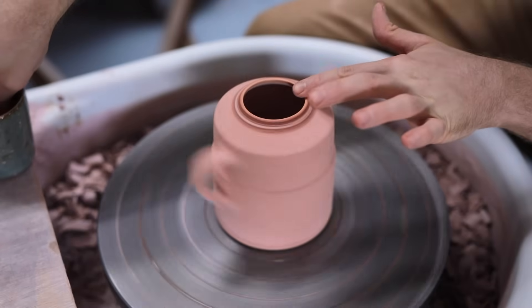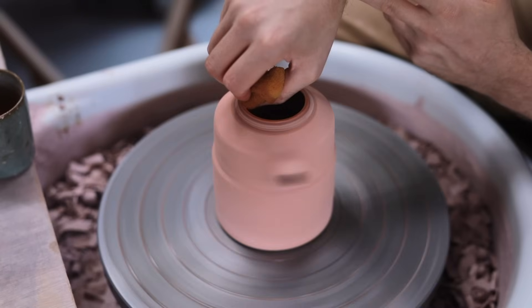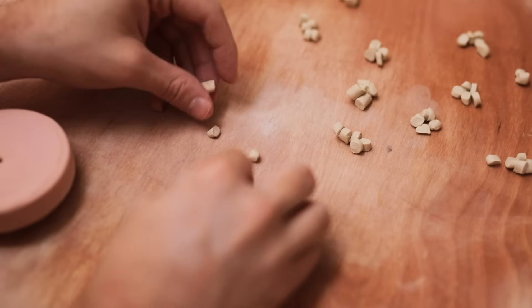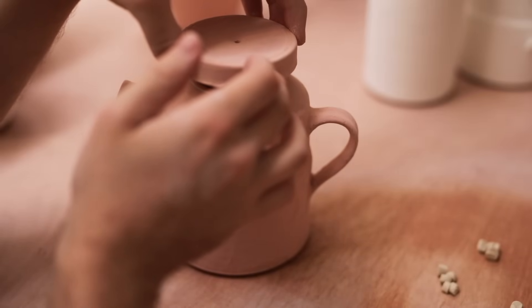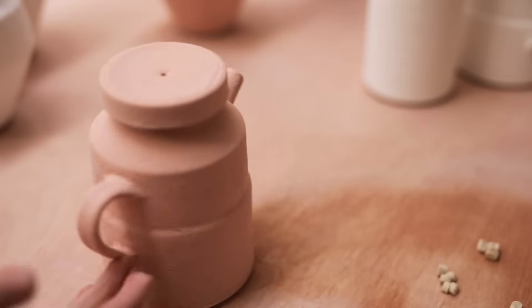I need this portion of the teapot's rim to remain bare, as I'll be firing both the teapot body and the lid together, with small discs of wadding separating them. Wadding is a highly refractory material which I mix up from 50% china clay and 50% coarse alumina hydrate. I mix it with water into a clay-like consistency, then roll it out and slice it into individual lumps, which I press into discs and carefully position around the lid. They easily stick onto the wax surface with just a touch of pressure, and as long as they're only touching the regions of bare clay, they won't stick. The lid is then carefully lowered onto the body and placed in such a way that neither part is touching the other, apart from the waddings separating them. Firing the two components together saves a lot of space in the kiln, and it also ensures that the two will match one another.